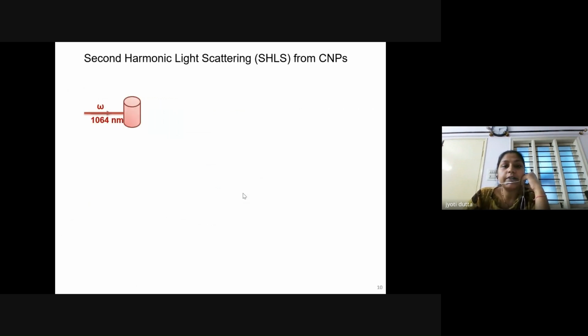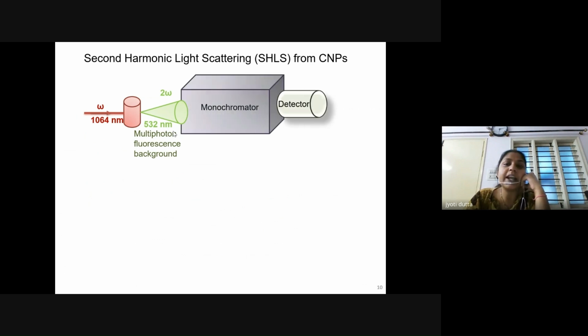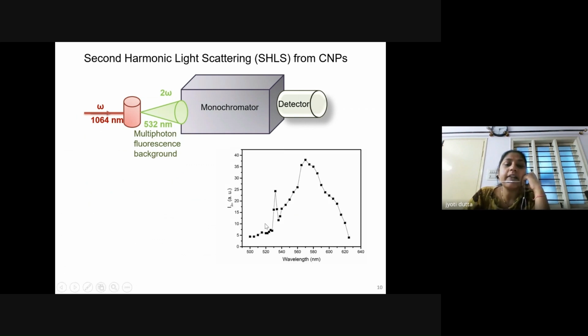So further, I would like to show in detail that we are incident with 1064 nanometer radiation on the sample of carbonaceous nanoparticles, and the scattered light, which will have a wavelength of 532 nanometer, was dispersed through a monochromator and was detected. What we observed is that for these carbonaceous nanoparticles, when we dispersed the incident radiation using a monochromator over the detector, the second harmonic signal is associated with a multiphoton fluorescence background.